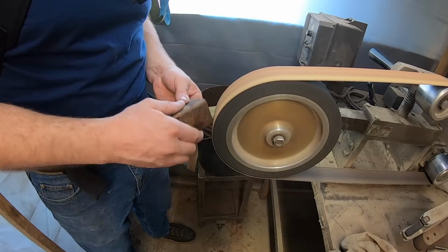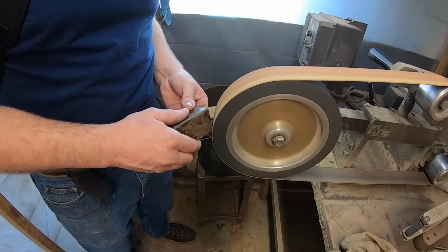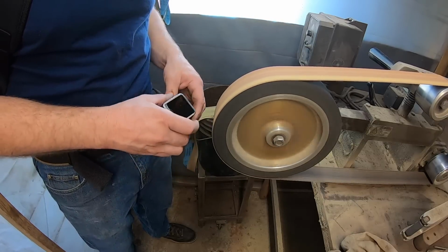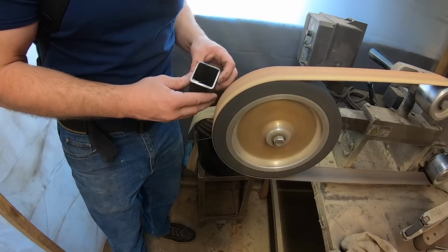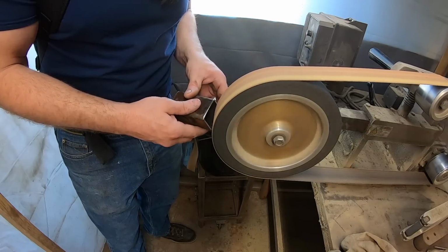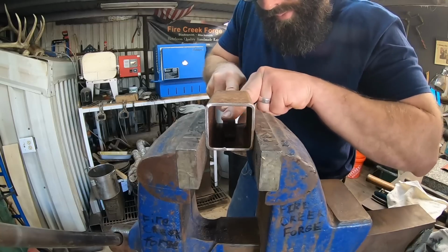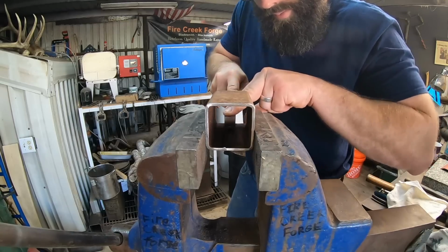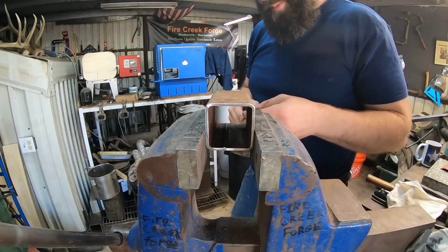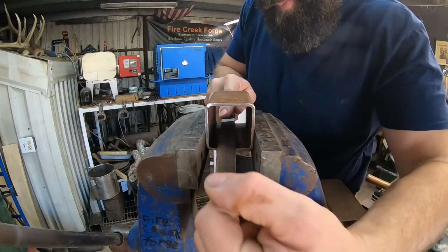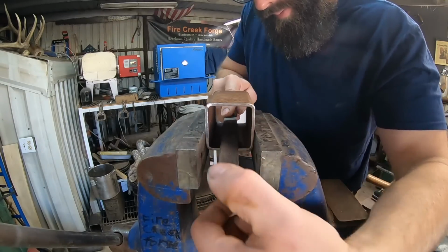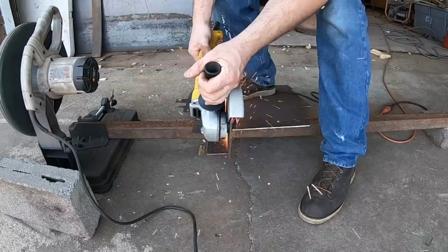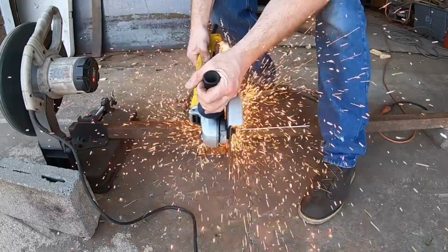So as usual, I'm using some mild steel square tubing to create a can to put these pieces of high carbon steel rod into. Go ahead and deburr it because experience has taught me that if there's something that I'll cut my finger on, then I probably will. And removing the seam from the inside, because if I don't, that will show up on the finished billet afterwards and will have to be addressed.